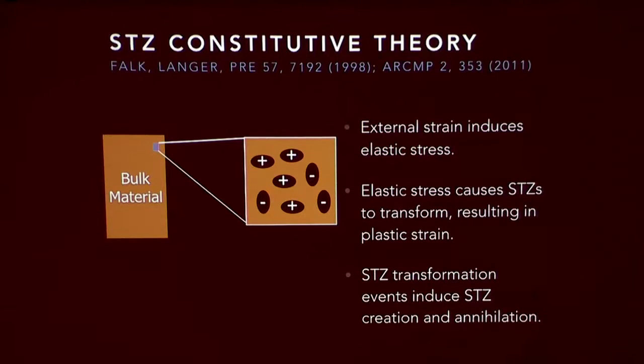Okay. So then the picture that had developed from this, and that we've been working on, is that we can write down a constitutive theory. If we have a theory of the micromechanics of what's going on in the glass, then we could use that as a basis for coming up with a theory of how the glass is going to deform. And the basic cartoon of the theory would be that if we take a bulk material and apply some load to it, some stress, there are these defects, these point defects essentially riddled throughout the glass. They have different orientations. And then under the effect of that applied stress, some of them are able to flip to align with the applied stress.